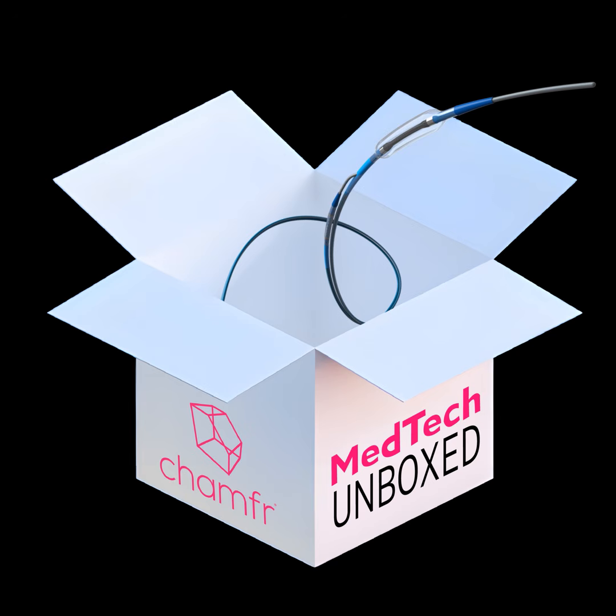And also, imagine back to our conversation earlier, in the very distal tip, how do I get it more flexible? If I'm still restricted by a high stiffness polymer like PTFE, then it doesn't matter how good of a laser cut pattern I get at the distal, it's still going to be somewhat rigid. Or you can force it, but you may brittle fracture that liner material. So in that kind of application, the lower durometer thermoplastic comes in handy. Number one, it will naturally bond to the stainless steel because it's nylon based, so you solve that reflow window problem. And not only that, because it's a lower durometer material, it will allow that distal section to flex better because it's more elastomeric, with a lower yield point, flexible. So that is kind of a big discovery we have found, that a lot of people want to utilize this material in a challenging design using laser cut.